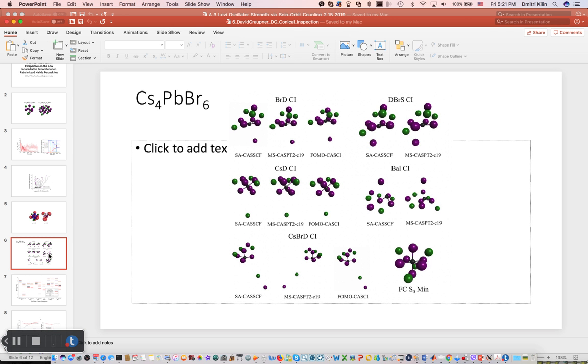So why did they do this? Because they were looking to find in what orientation it was more likely to get the conical intersections. So what kind of motion of which atoms, what geometry makes the S1 minus S0 gap equal 0? Yes. Or at least closer to 0.